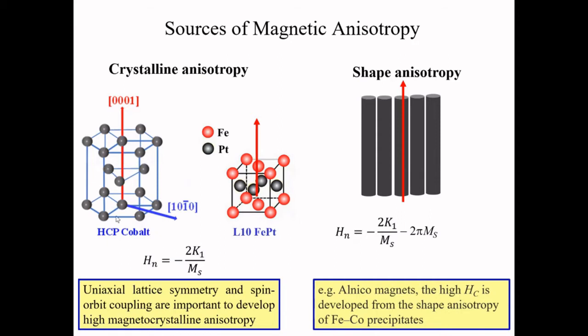When we put the spin in a crystalline structure, it depends on the crystalline structure, they will have a preferential orientation. Like here I talk about HCP, the spin has a preferred orientation along the C-axis. Like here, the L10 tetragonal FePt structure, the C axis is the easy axis. Okay, so these are particularly related to the material.